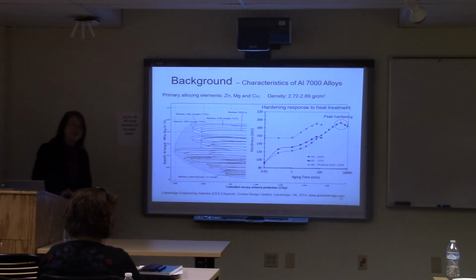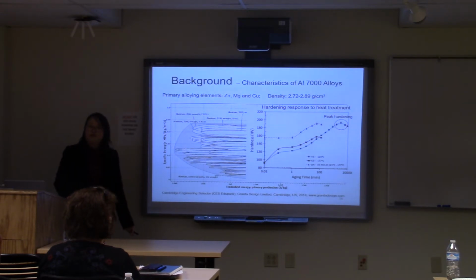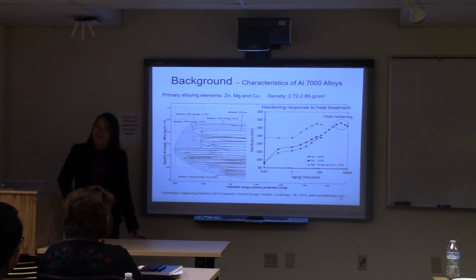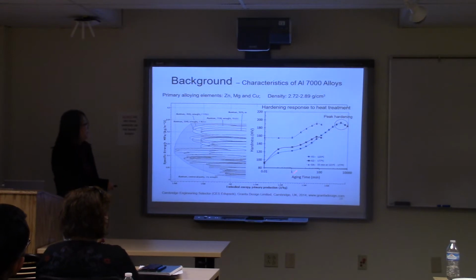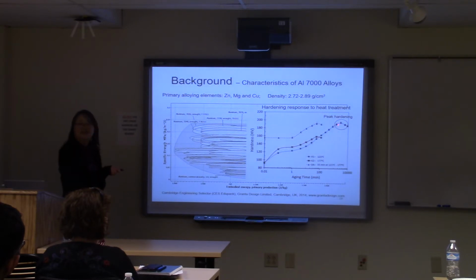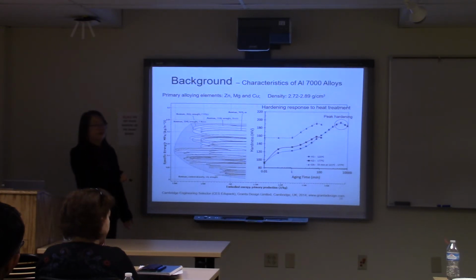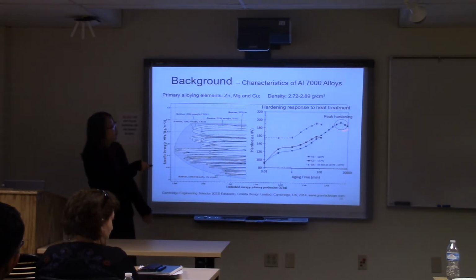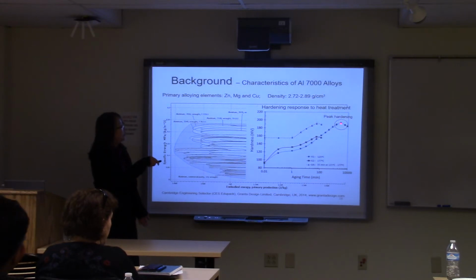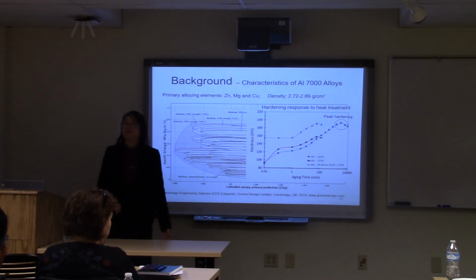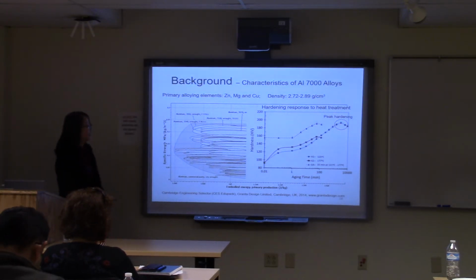It's a very special class of alloy, which we usually call heat treatable alloys. So upon heat treatment, this is the hardness. The hardness of this alloy can increase upon treatment until it achieves a peak hardness. And if you continue to treat that, you will get softening. And in industry, they usually call this condition the T6 temper, where you get the highest hardness here.